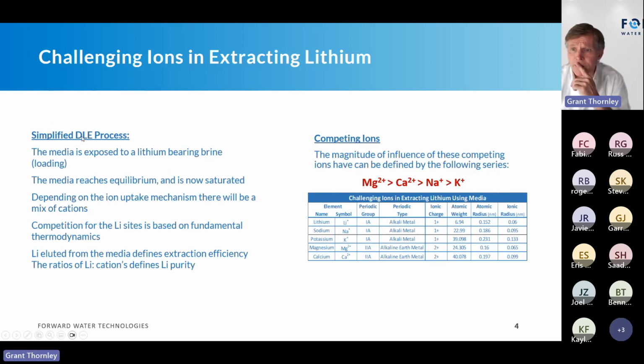So when we talk about a simplified process, media is exposed to lithium brine. When you load up the media, it reaches equilibrium, meaning it's fully loaded. When we say fully loaded or saturated, it doesn't necessarily mean that it's all lithium. It can be other contaminants, such as magnesium, calcium, sodium. So depending on the ion uptake mechanism, there will be a mix of cations. Of course, we want pure lithium coming out through the eluate, but we know that isn't reality. What we get is a ratio of magnesium, calcium, and sodium.